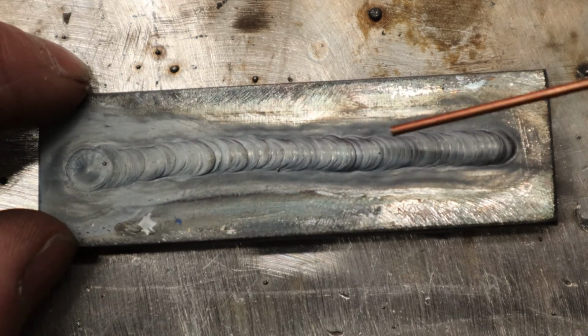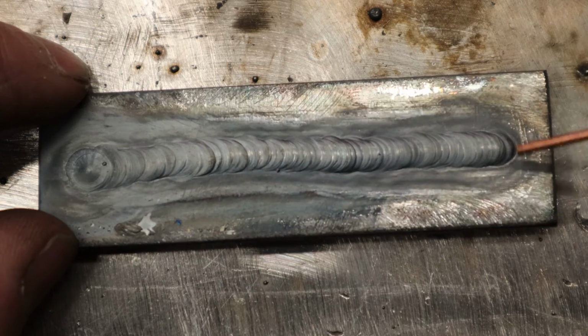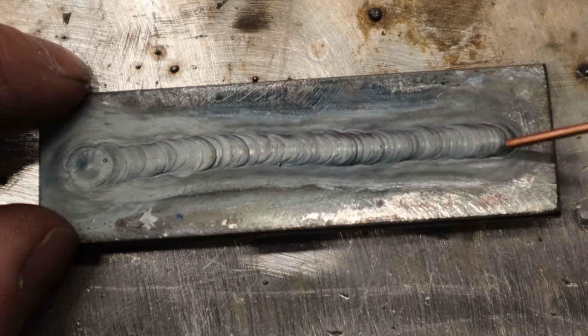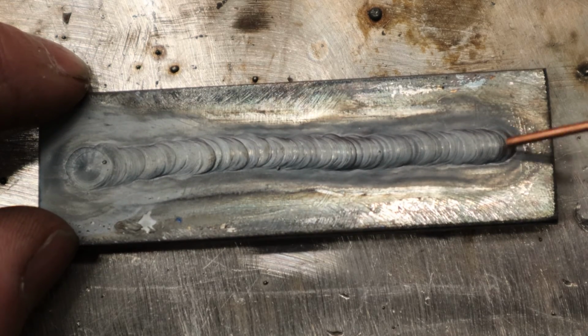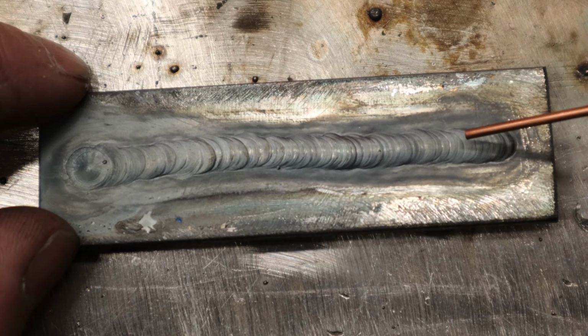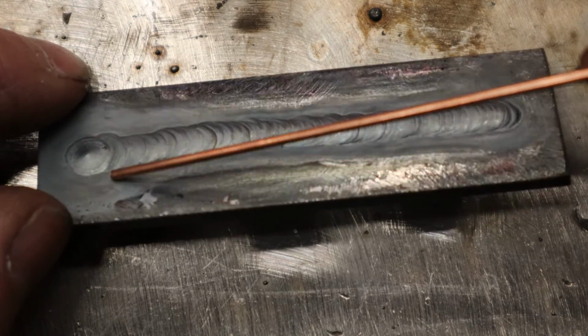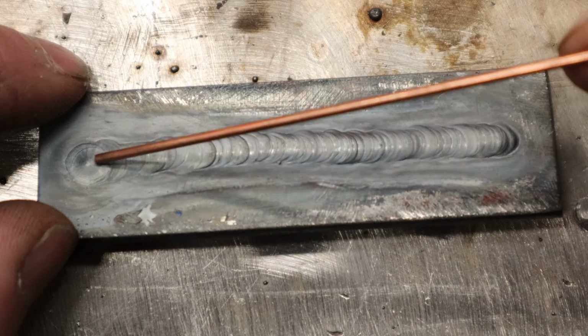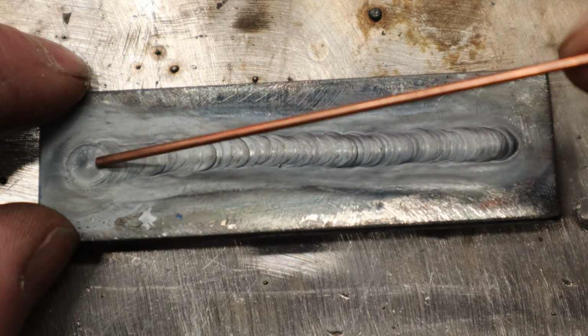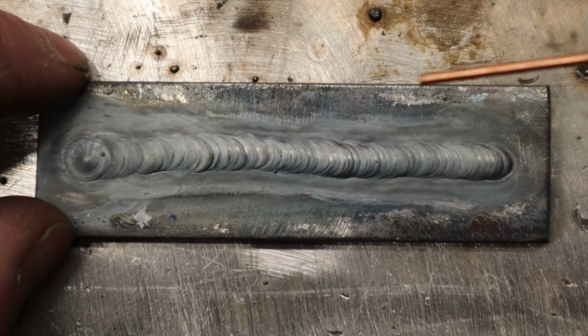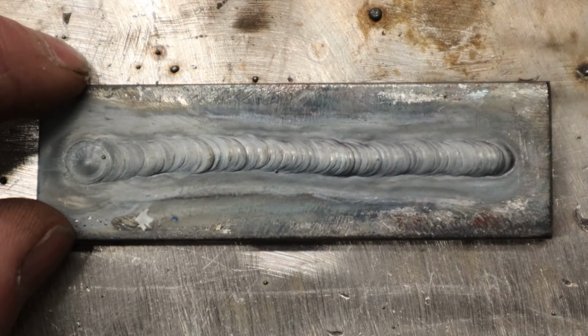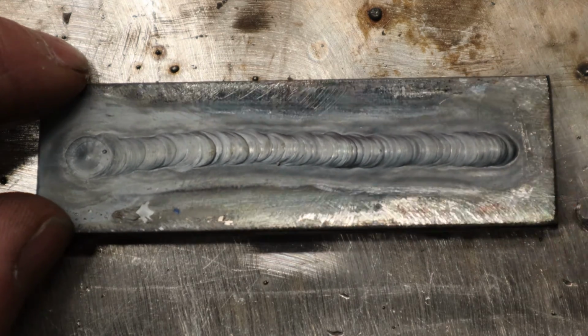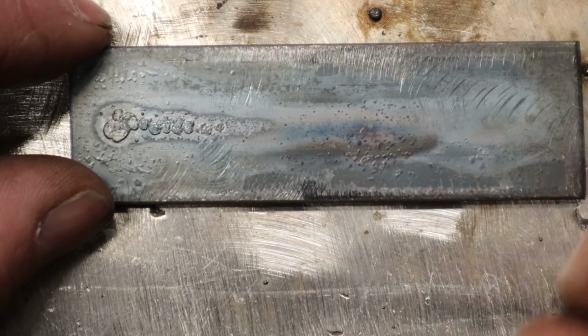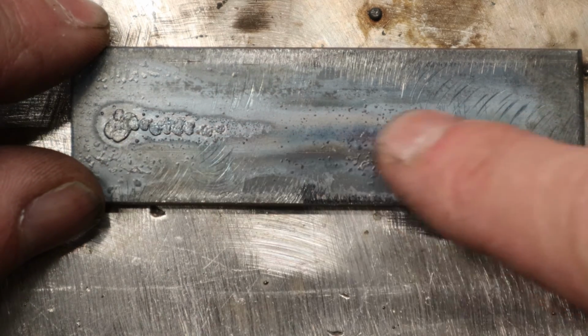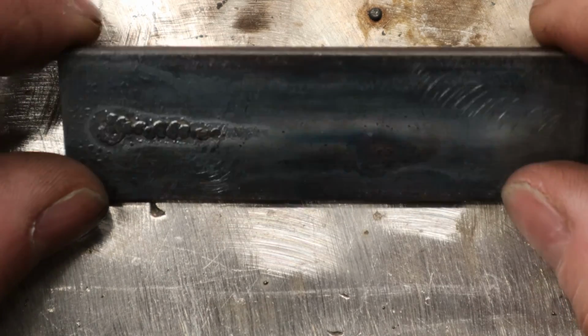There is not a single pinhole in this whole thing. There is no crater at the beginning of this weld, so I paused long enough to get some material in there and get a bead started before I started moving away. At the end, hard to see. You probably could put a little bit more filler rod in here to cap it a bit better, but definitely not a crater. No pinholes. And let's see for strength. You can see there's a little bit of melting through in the backside, so definitely a strong weld as well.